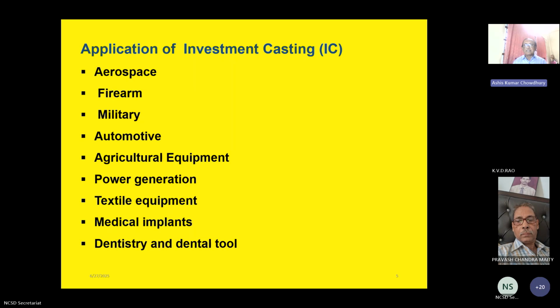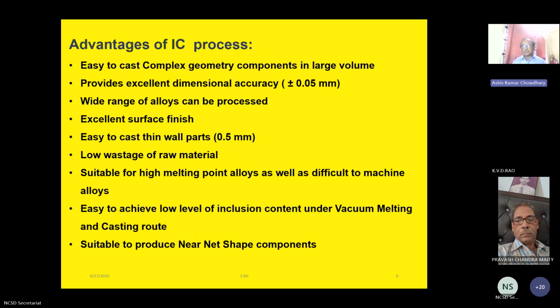There are a lot of advantages of the investment casting process. Some of them are: easy to cast complex geometry components in large volume. Number two, provides excellent dimensional accuracy, plus minus 0.05. Wide range of alloys can be processed. Excellent surface finish, easy to cast thin wall parts, low wastage of raw material, suitable for high melting point alloys as well as difficult to machine alloys. Easy to achieve low level of inclusion content under vacuum melting and casting, suitable to produce near net shape components.